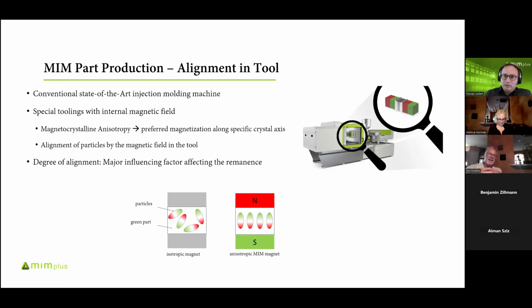Because again, a lot of interesting things have been done with magnets, but they either end up with bonded magnets or they end up with isotropic, right? Which means you're not going to get really strong magnets. You've solved all of those problems where not only have you gotten rid of the binding material, but you've also been able to align the domains such that they optimize whatever the function is. Exactly. And that's also something we always have to explain to our customers, which is very important to understand, because the degree of alignment, like you said before, is really critical with regards to the remanence. So we need to achieve a very high degree of alignment to achieve a high remanence in our magnets.